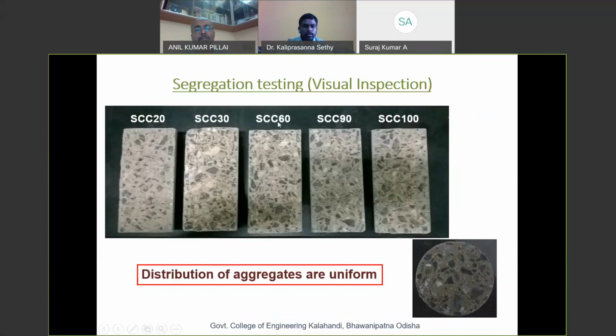And though we are developing flowable concretes, there may be a chance of segregation, and there may be a chance of settlement of the coarser aggregate at the bottom of the frame structures or mold. But you can see here, all the concretes which we have developed, that self-compacting concretes from 20 MPa to 100 MPa, show a very good uniform distribution of these aggregates throughout the samples. So you can say it is a very good concrete, showing very good fresh properties.